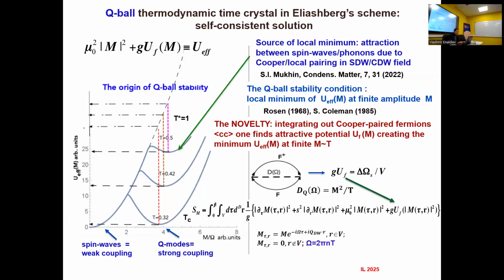So, what is important here? Finally, we found this contribution to the free energy, to the Euclidean action of the whole system. It means that we have integrated out fermions, and we got this effective energy of this M field that forms a Q ball. And now it's interesting to see how this effective energy looks like. And it proves to be like this.